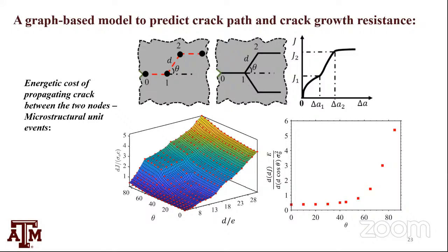That's the one part, because we're assuming that it's always going to follow the microstructure. So we did try to analyze that: if there's a grain boundary case, if I have all of a sudden a grain boundary step that just goes 90 degrees, so it goes asymptotically up, right? In that case, it can capture an arrest, but the arrest is coming from the microstructure. But in some cases, when we are loading the material, it gets trapped for other reasons, largely driven by plasticity, because the fracture is history dependent. If it's largely driven by some weird thing in plasticity in the material, then yeah, it cannot predict. We do need to know all the unit circumstances for it to work. Right. Thank you.